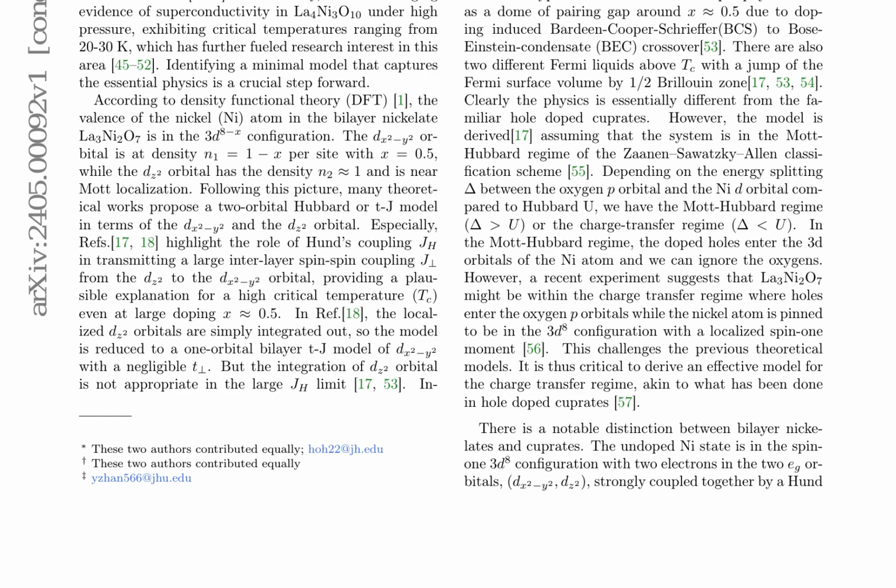Additional DMRG simulation results are presented, including the t-parallel dependence with varying interlayer repulsive interaction strengths V. These results demonstrate how the non-monotonic decreasing region diminishes and eventually disappears as V increases. The authors also provide DMRG simulation data at x equals 0.2, which exhibits similar key characteristic behaviors to the data at x equals 0.5 presented in the main text.